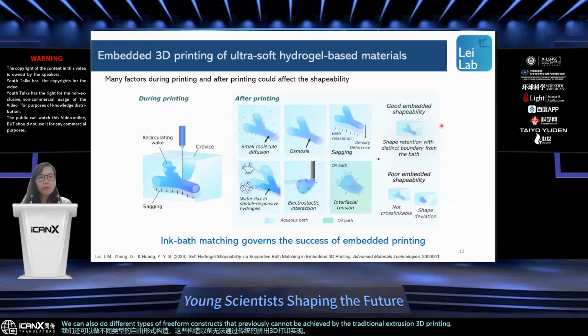The concept of embedded 3D printing seems very simple, but the actual process is quite complicated because there are two phases involved in embedded 3D printing. Therefore, there are many factors happening at the ink and bath interface that could affect the shapeability. During printing, there could be quite fast recirculating rate and sagging if the rheological properties of the ink and the bath are not matching.